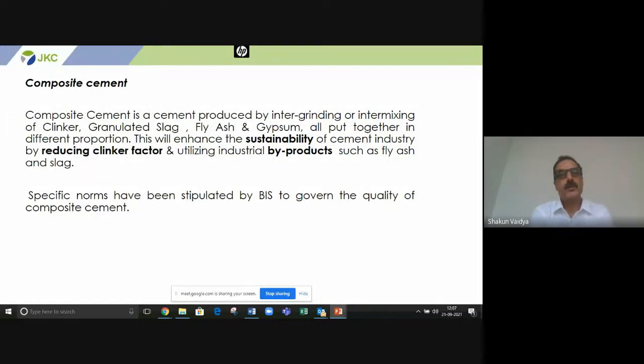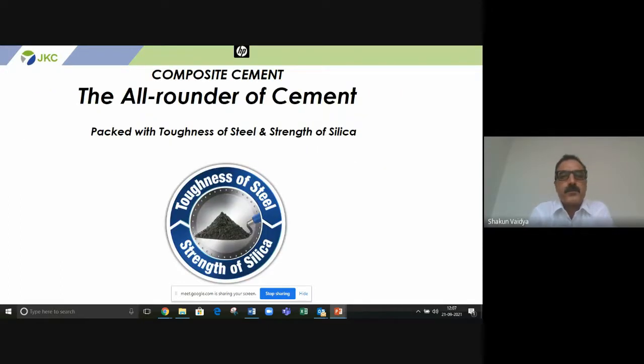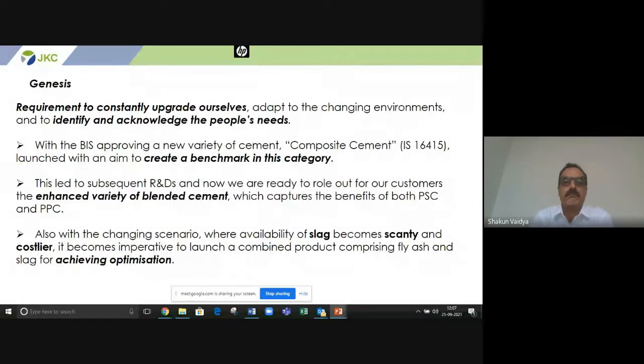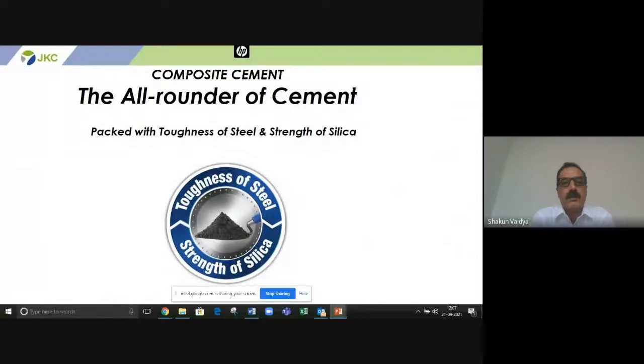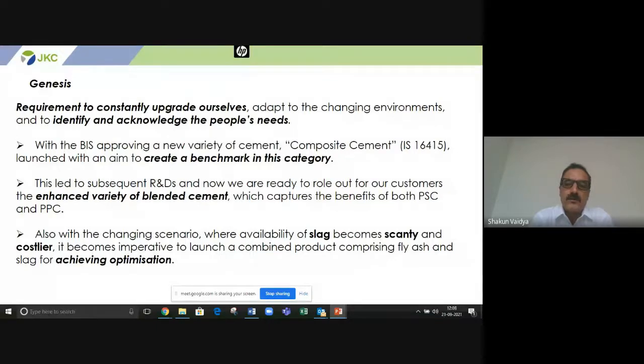So composite cement is produced by intergrinding or intermixing of clinker, granulated slag, fly ash and gypsum. This will enhance sustainability, reduce the clinker factor, and effectively use byproducts such as fly ash and slag. It is an all-rounder, you would say, because we can say that it has the toughness of steel and strength of silica. Slag, though not steel, is a byproduct of the steel industry, and the silica is very reactive. So in a two-way, it has both the properties of PPC and PSC.